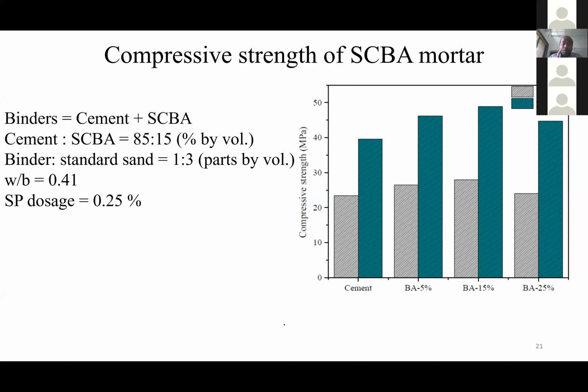Otherwise, depending on how the sand is packed, the strength will be influenced and standard deviation will be more. Since we have been doing this particular practice for the last 10 years, we are not having any issue so far. Our standard deviation between 3 specimens tested is very, very less, which means we are more consistent. And whatever we claim as the influence of this SCBA is getting reflected clearly and evidently.